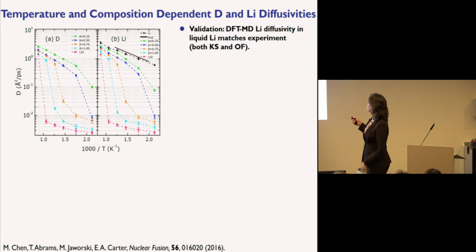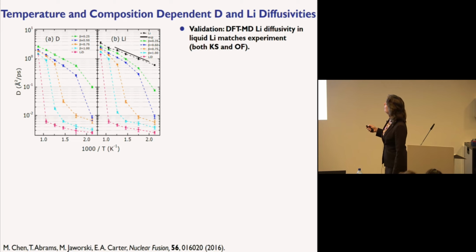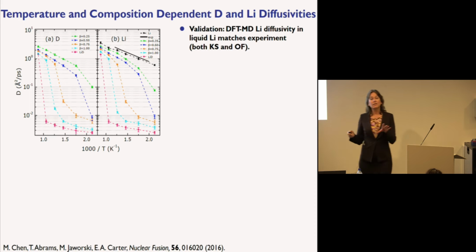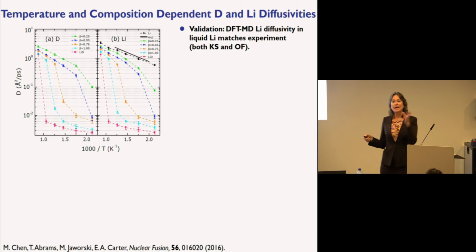And what I can tell you, this is now looking at the diffusivity of deuterium and lithium as a function of inverse temperature. What's shown in black here is pure lithium. The black symbols are the Kohn-Sham MD simulations, which match experiment very well. Orbital-free does equally well for pure lithium, but we can't do anything else. So we can't look at what happens when we add deuterium.